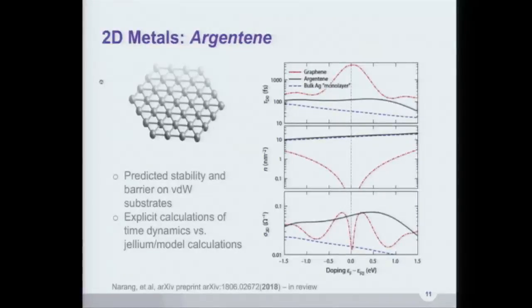Okay? And we predicted a new material, Argentene. We predicted the fact that it's stable. Now, we weren't the first to say you could make metals a monolayer, but most previous work in thinking about metals as monolayers treated them at a jellium level. So essentially it said that it's the same as the 3D case, just shrunk down to 2D. Turns out that when you explicitly calculate the material, it adopts a slightly different structure than just taking that 3D case and forcing it down to a 2D case. And this is, again, an argument for why explicitly calculating it, rather than using a jellium or model calculation, would have given you qualitatively and quantitatively different results for the same material. Okay, so this is Argentene.